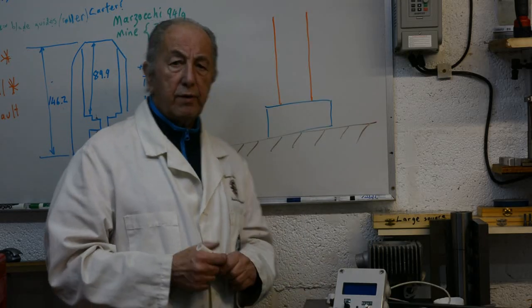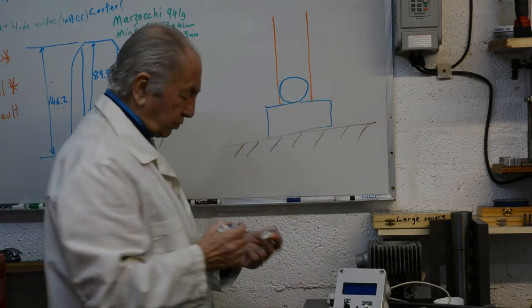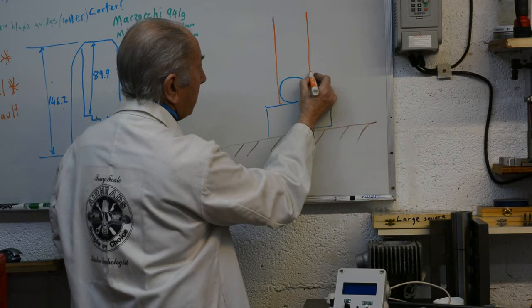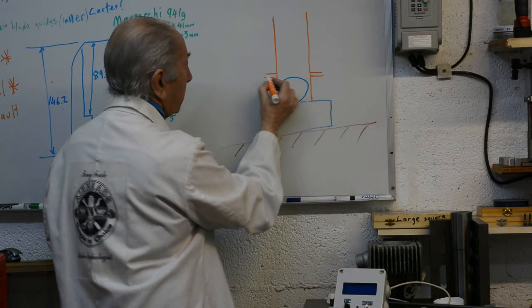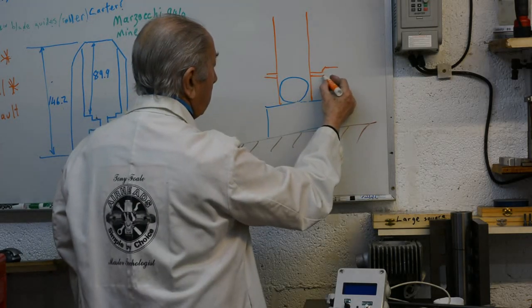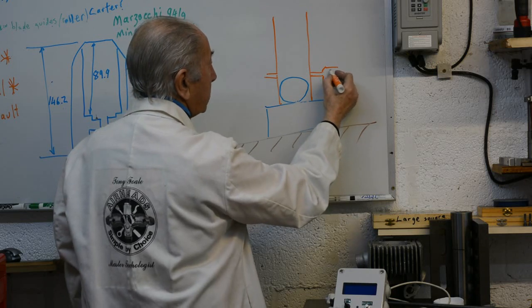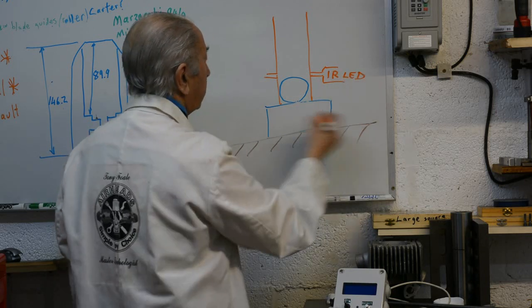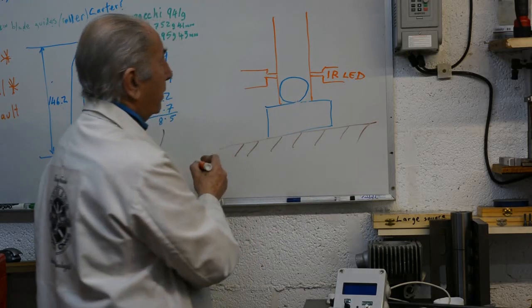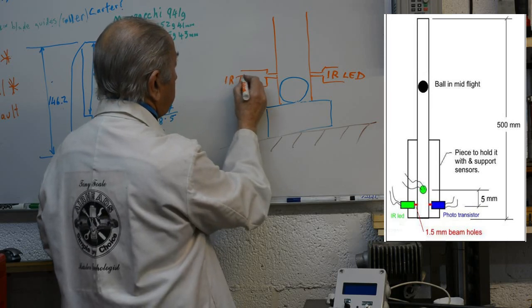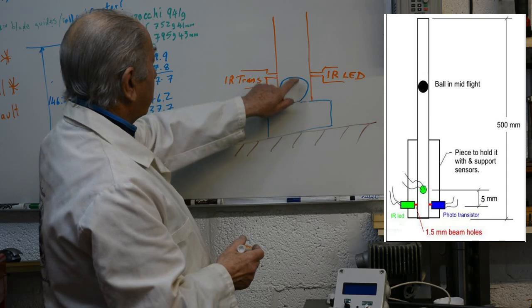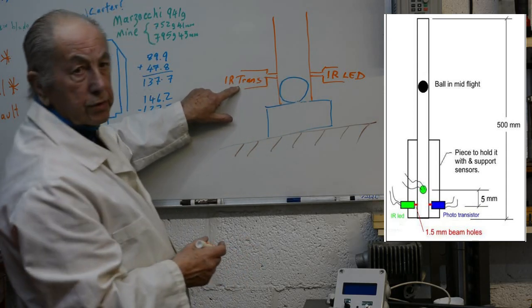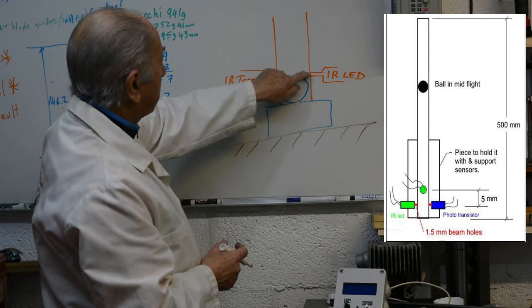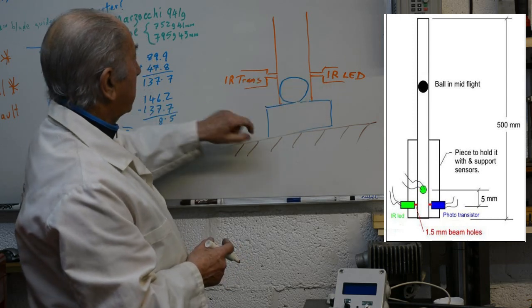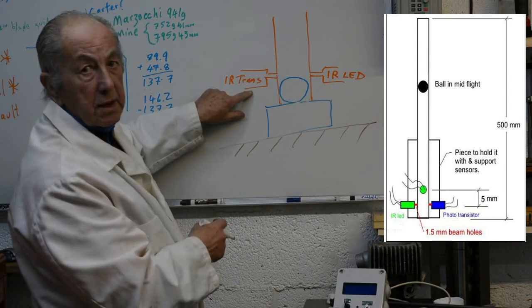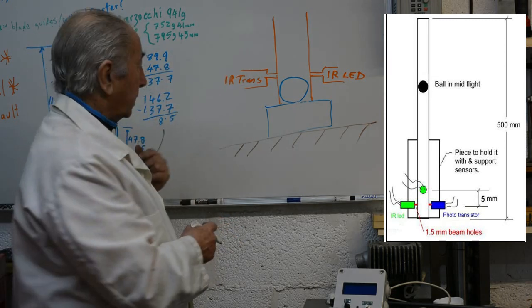Let's look at how I actually measure the velocity. This is our tube. Ball has dropped to the bottom. Just above that, I have opposite holes drilled and then enlarged. In one I fit an infrared LED, and in the other one, in the enlarged part of it, I fit an infrared transistor. So this one passes light across. If there's no ball in the way, the light comes through and the transistor picks it up. When a ball is in this region, it blocks off that infrared light, and the infrared transistor detects that, and that's passed on to the processing electronics.